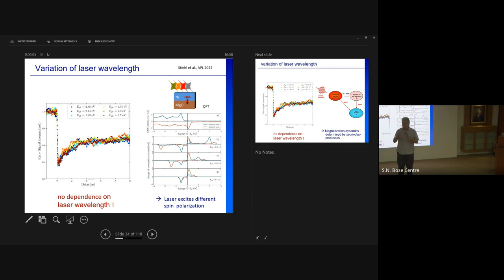Okay. You pump just the nickel film, let's say the 10 nanometer nickel film, and you probe the difference between majority and minority electrons. And there are two effects. Either they flip the spin, or one of them moves away, wherever they go. And when they move out, you do not probe them, and you have neutral spin electrons back, that also reduces the magnetization. It's the transfer of angular momentum due to the spin transport into the gold or into the copper, whatever substrate you have. But that seems to be very fast. It is halfway ballistic and halfway diffusive, so it was called super diffusive. Maybe the right word or not.